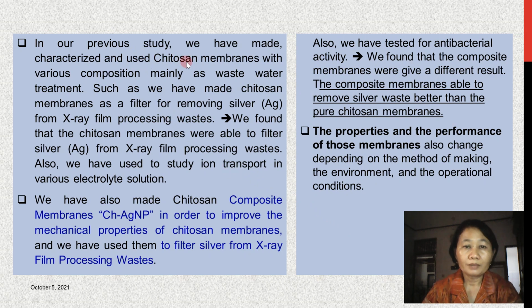In our previous study, we have made, characterized, and used chitosan membranes with various compositions, mainly for wastewater treatment, such as a chitosan membrane filter for removing silver from X-ray film processing waste. We found that the chitosan membranes were able to filter silver from X-ray film processing waste. Also, we have used them to study ion transport in various electrolyte solutions. We have also made chitosan composite membranes Ch-AgNP in order to improve the mechanical properties of chitosan membranes, and we have used them to filter silver waste from X-ray film processing waste. Also, we have tested for antibacterial activity.